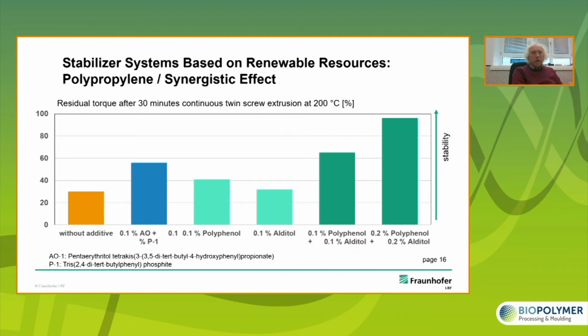So what could be found? First of all, if there's a polypropylene without stabilization, of course within 30 minutes at 200 degrees, there is a high damage. That's to say, the loss of the residual torque is at 70%. Adding the usual stabilization with phenolic antioxidants or phosphite, here P1, then we will see an improvement. We have 60% of the original value still after this 30 minutes.